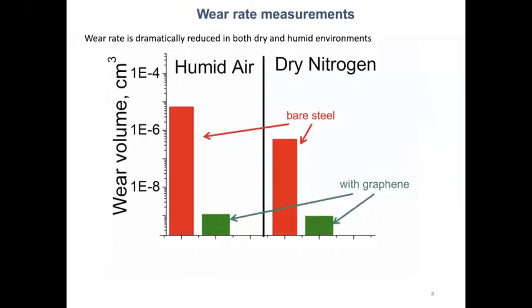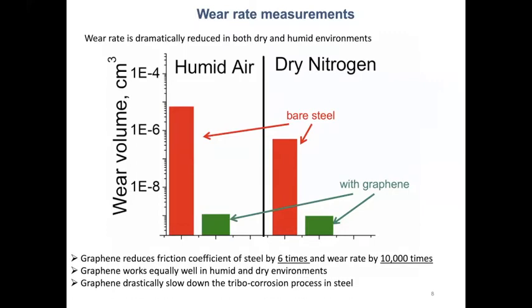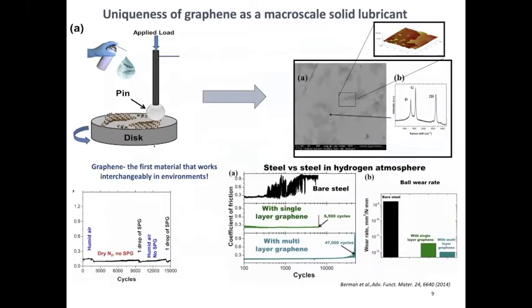It also compares well in terms of wear, both in humid air and in dry nitrogen environment. We see significant improvement in the wear resistance of our surfaces. In this case, it's 4 or 5 orders of magnitude reduction in the wear of the steel surfaces. And what is interesting is that if you look at the SEM image of the graphene covering the steel, it doesn't really require a uniform, high quality coating on the surface. It's enough to have just sporadic flakes of graphene on the steel surface to demonstrate this very good protection. You can also see some overlapping. So these grayish islands are the islands of graphene on the steel substrate.